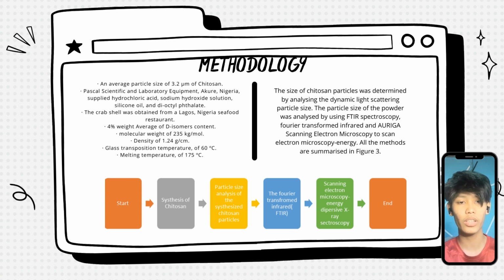The crab shell was obtained from a seafood restaurant in Lagos, Nigeria. We use a 4% weight average of D-isomer content. The molecular weight we use is 235 kg per mole. The density we use is 1.24 grams per cubic centimeter. We use a glass transition temperature of 60 degrees Celsius.